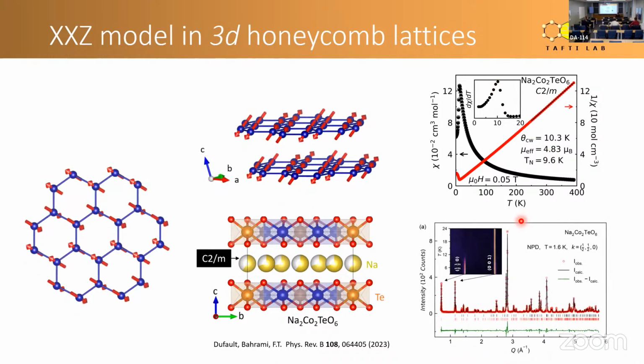But we basically found what the ordering in this system is from neutron scattering, elastic neutron scattering. It's a zigzag order.